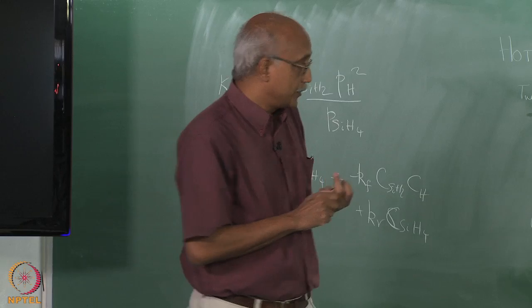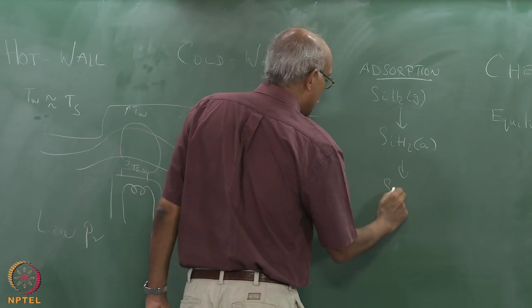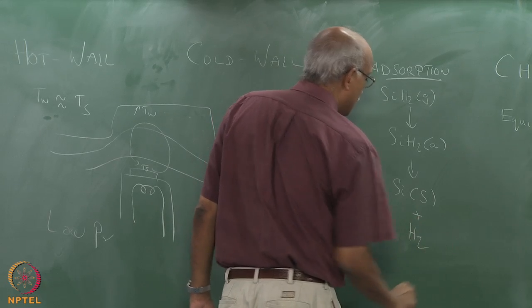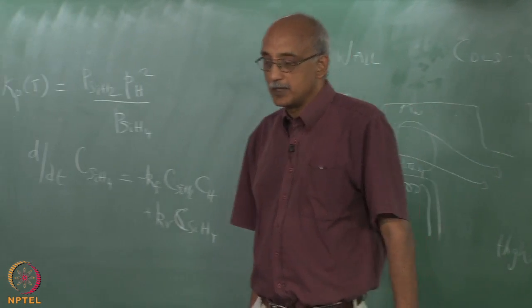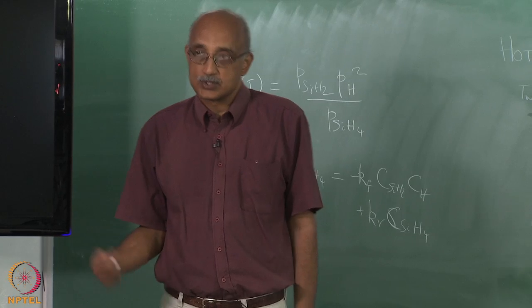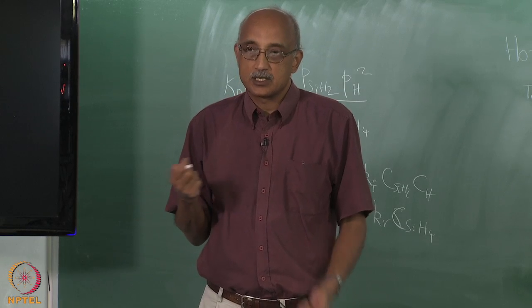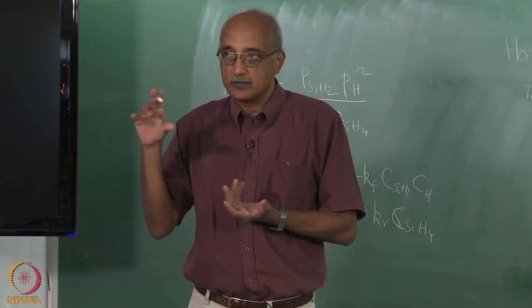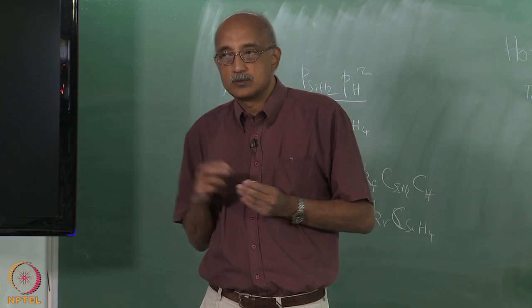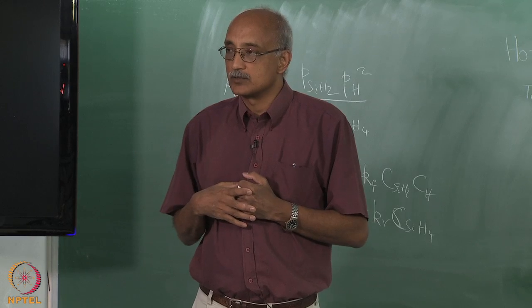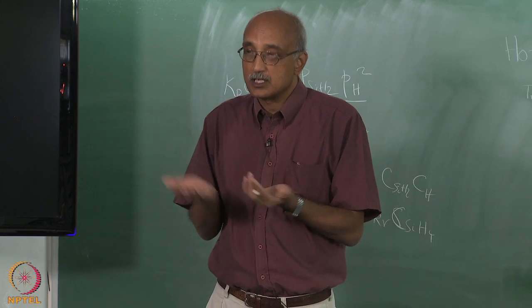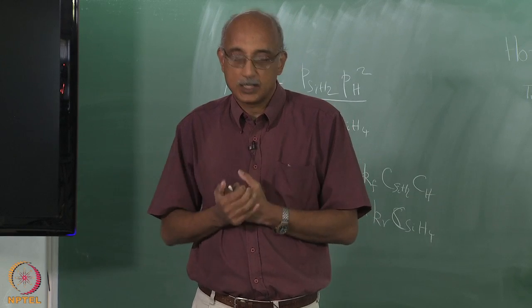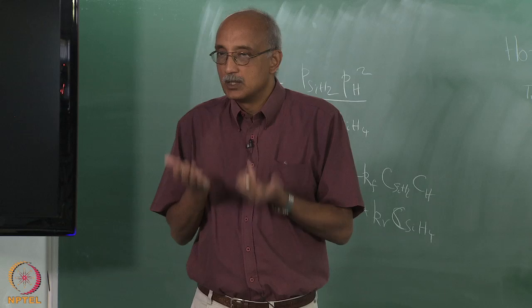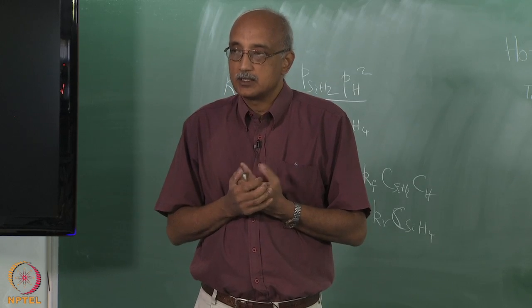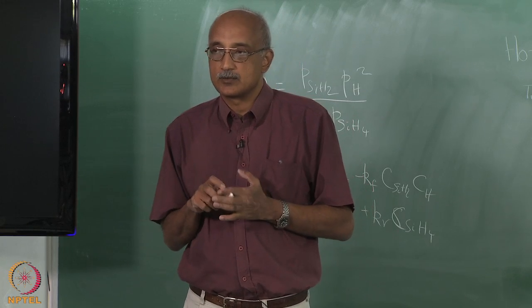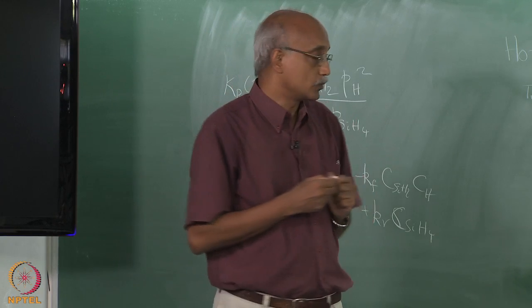So the next step from SiH2 adsorbed is for silicon to become a solid phase and release the H2 as a desorbed vapor. So that's the next step. And desorption also is a process that is enhanced by temperature. So temperature not only makes it easier for the SiH2 molecule to move around and find a vacancy and therefore lose the silicon, but it also makes it easier to desorb the hydrogen and get it out of the system. So those are all reasons why you want to keep the substrate temperature as high as possible. It makes for a much thicker film and a much more uniform film. So if you are trying to minimize your cycle time and improve particularly the uniformity of your film, then you are much better off using a hot wall setup compared to a cold wall setup.